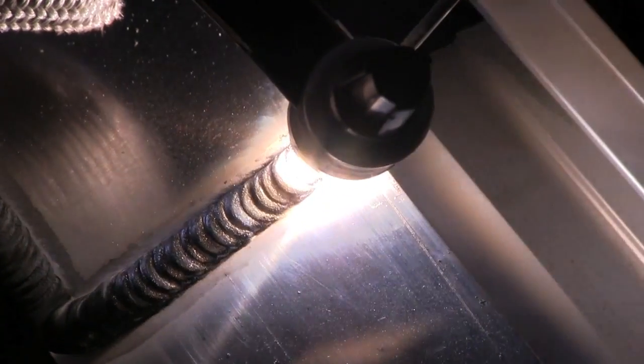This is one of those jobs where mixing a little bit of helium in with the argon, or using a pre-mix, something with maybe 50% helium, you would really notice a difference.